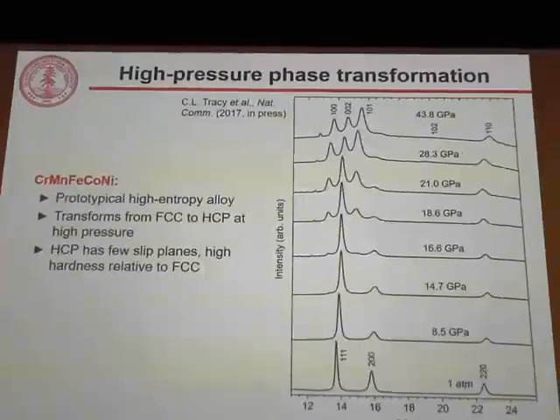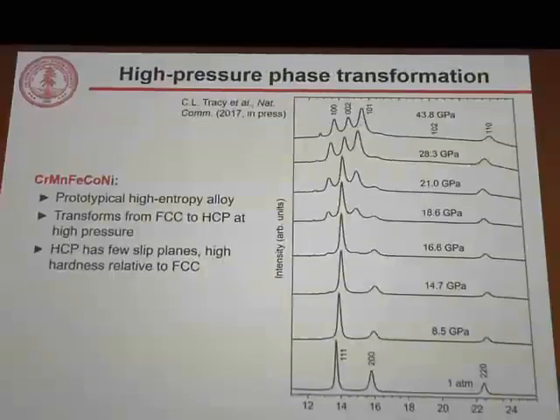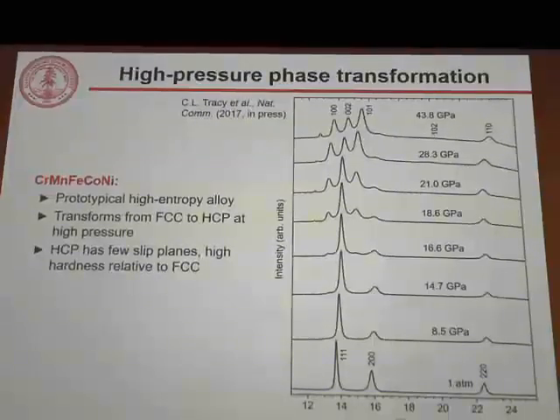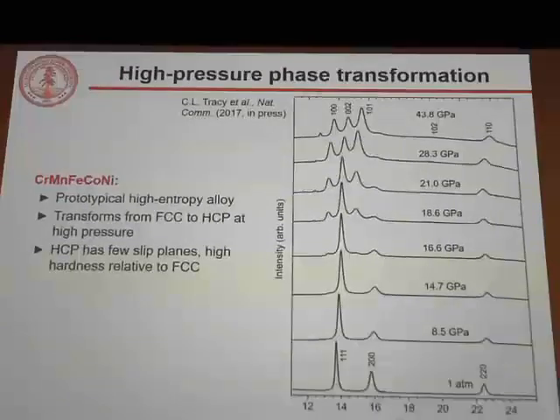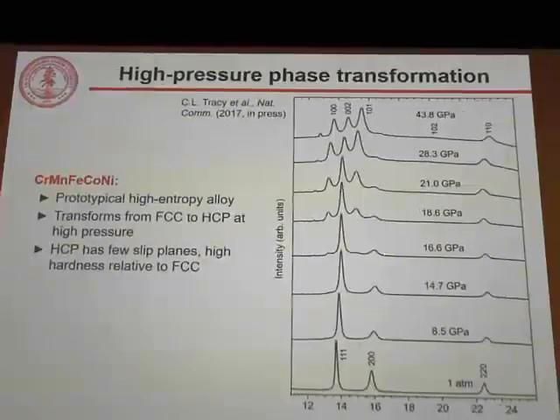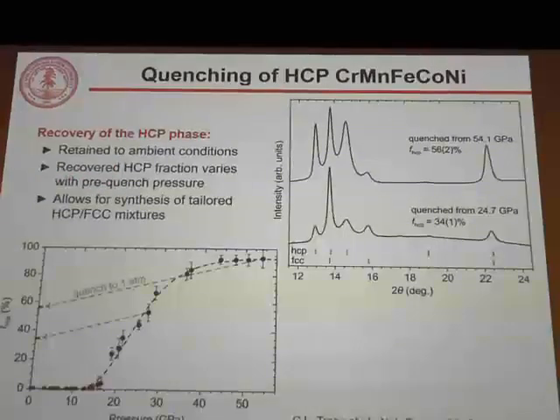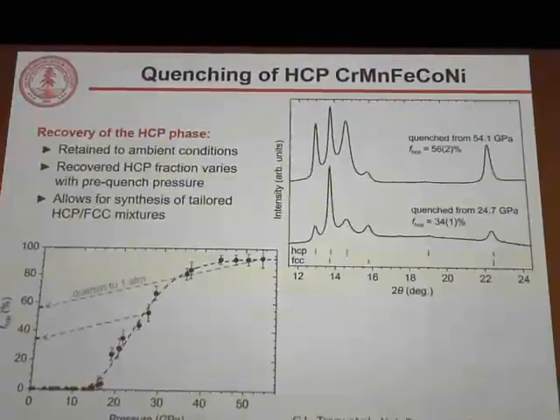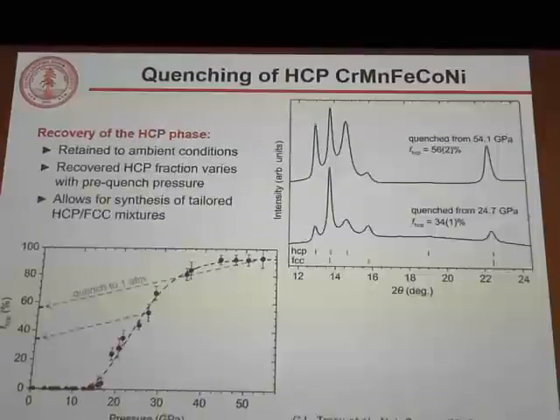We've now done this. It's useful because HCP materials have relatively few slip planes compared to FCC, making them typically quite hard. So hard materials are sometimes good, ductile materials are sometimes good. Regardless of what we want, we need to, again, quench this material to ambient conditions. So when we reduce the pressure, we quite surprisingly see that much of this HCP phase is retained.